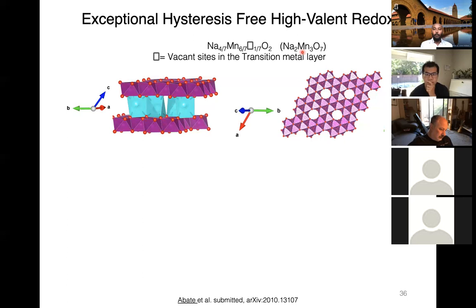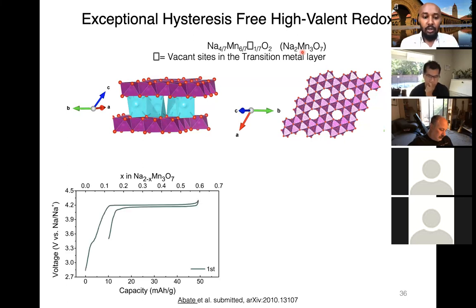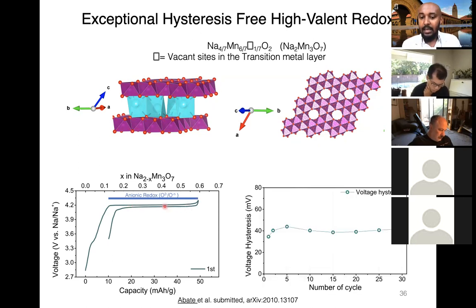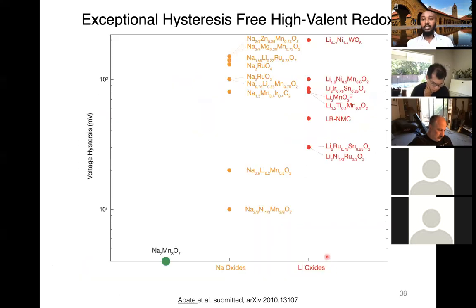If you perform anionic redox on this material, this is what it looks like. You have an exceptionally low hysteresis during charging and discharging. This low hysteresis is measured to be close to 40 millivolts, and that is maintained for several cycles as shown over here. If you compare this small hysteresis with previously reported lithium-based and sodium-based cathode materials, here is the log scale of the voltage hysteresis. Our material had a very small hysteresis compared to previously reported sodium or lithium-based cathode materials that had anionic redox.